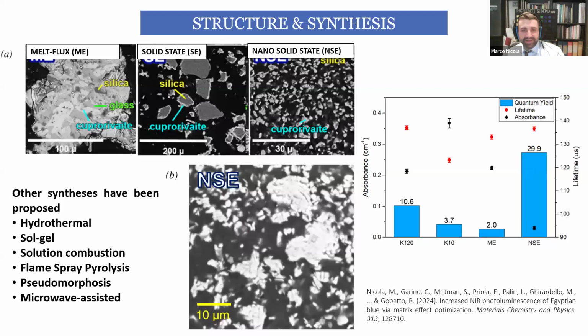So this is the possibility with two methods of production. With another method of production, we can avoid the presence of a bulk silica core in each grain of Egyptian blue, and we can improve dramatically the luminescence of the material because we have pure cuprorivaite, the active crystal in Egyptian blue, the one that is luminescent, without the glass matrix. The glass matrix instead absorbs the luminescence, so it is a kind of self-absorbing material. So if I can avoid the production of glass, I can improve the luminescence.